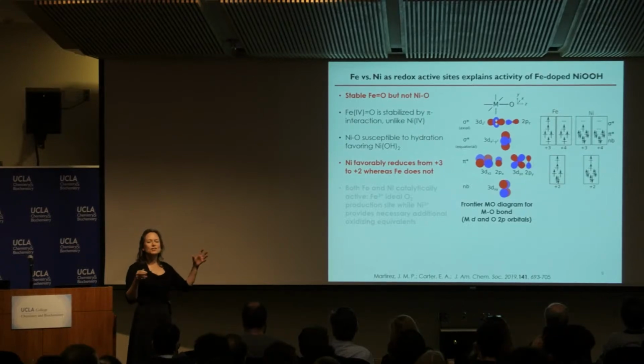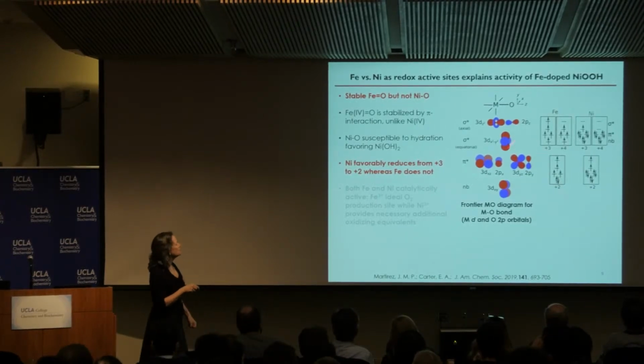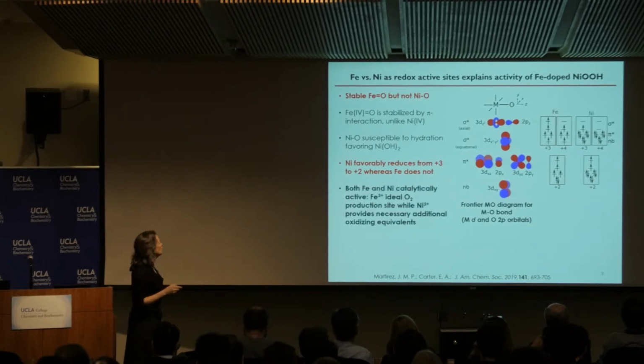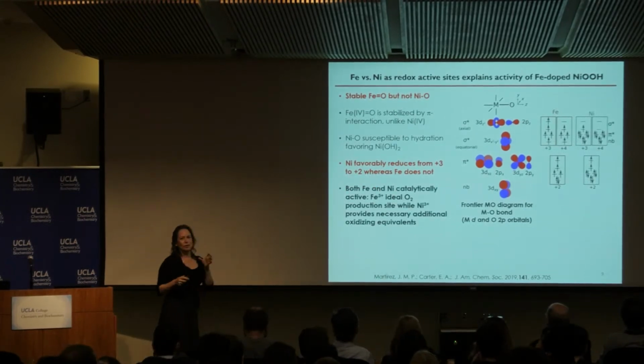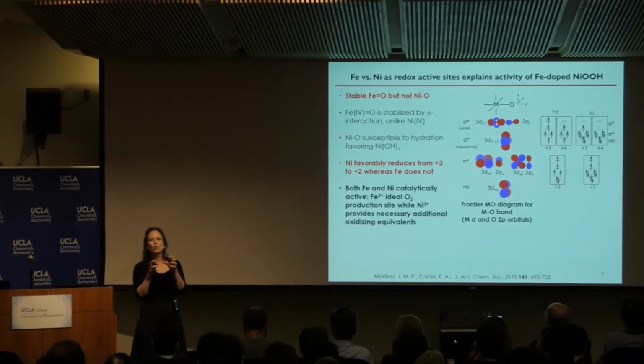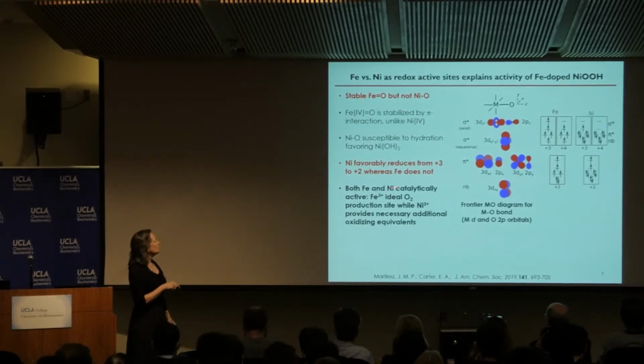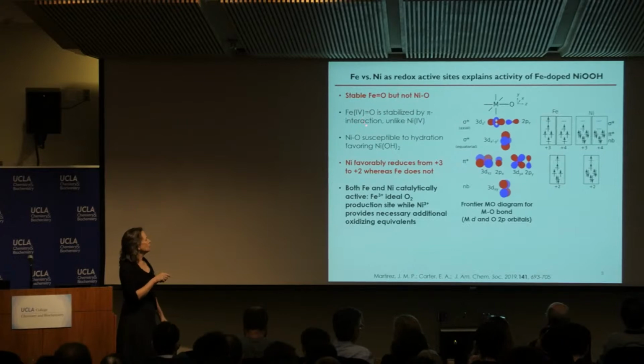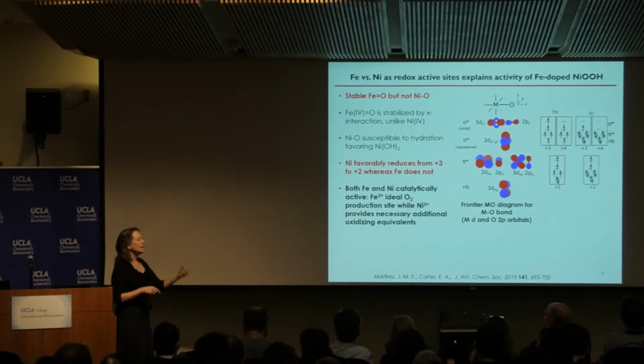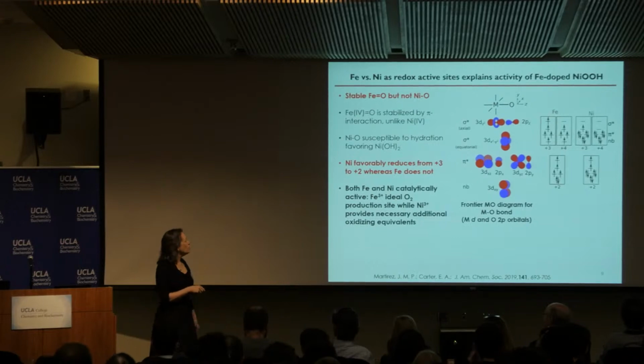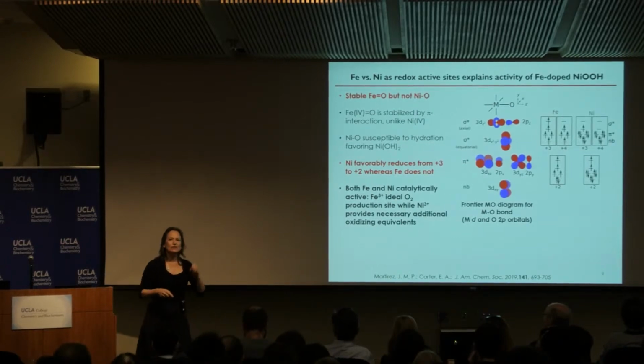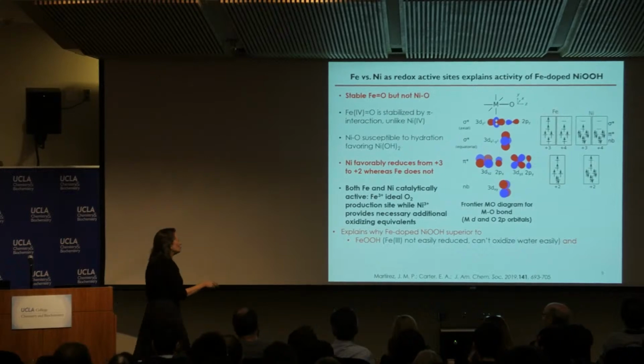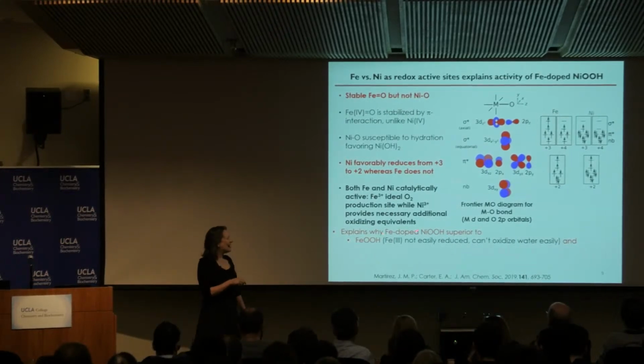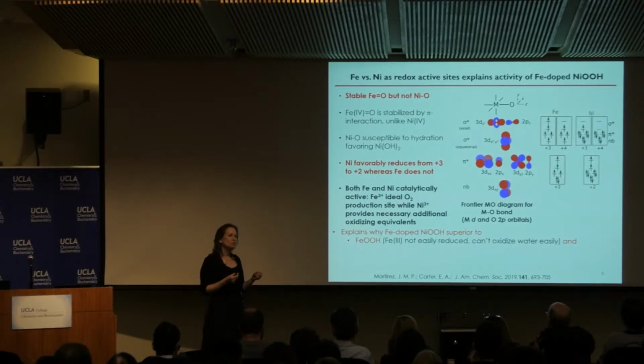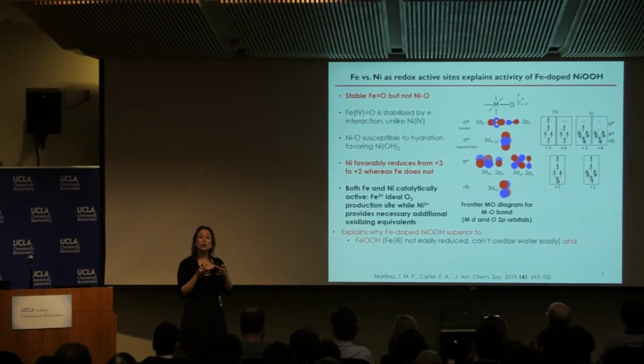Another way to think about it is it's the stability of the half-filled shell of the D5 state here. It doesn't want to add an electron. So both iron and nickel play these very symbiotic roles in this material. Iron 3 is the place that can make this O2 by forming first this iron oxo, whereas nickel 3 plus can pull electrons out of water in order to make nickel 2 favorably, whereas iron 3 can't do that. And so it's a really beautiful way to understand why this iron-doped nickel oxyhydroxide is so much more favorable than any of the pure materials.